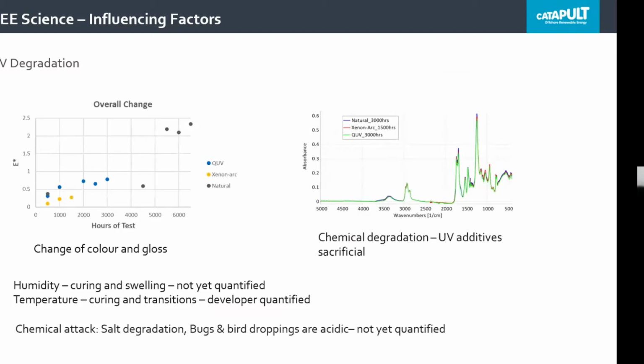So in terms of UV degradation, some of the studies that we've been doing, weathering has been really well understood by individual coatings manufacturers for decades, and individual materials, but the correlation and combination of weathering with rain erosion is still a really low TRL level process. Some of the research that we have done so far, we've looked at changing color and gloss under both natural weathering and under 2 accelerated weathering test methods, QUV and Xenon Arc, as you can see on the left for delta E, that's the change in color.